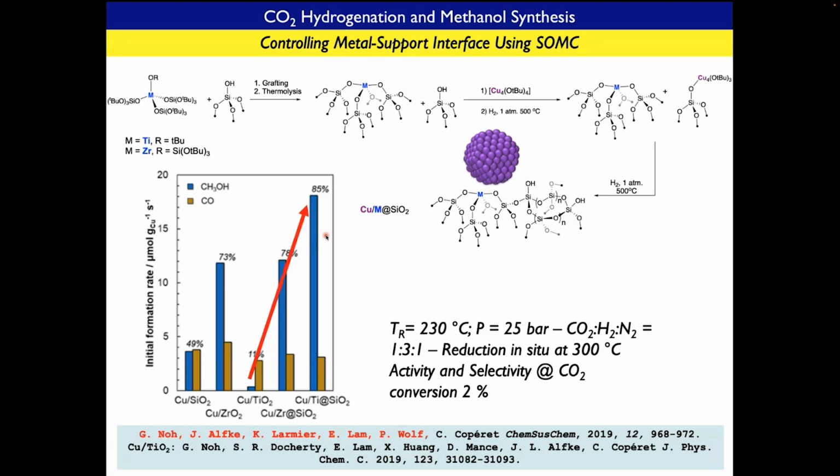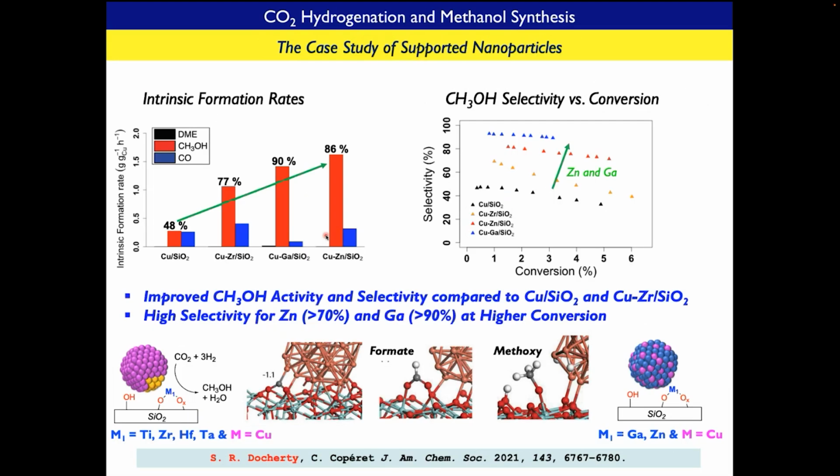And in a way, it relates to what we said earlier with gallium on silica for PDH. In the case of gallium oxide, we could show that it reduces very fast and leads to a poorly stable catalyst. When you have isolated gallium sites in silica, an insulator, you can keep activity. So you can see there is a relation between the two systems.